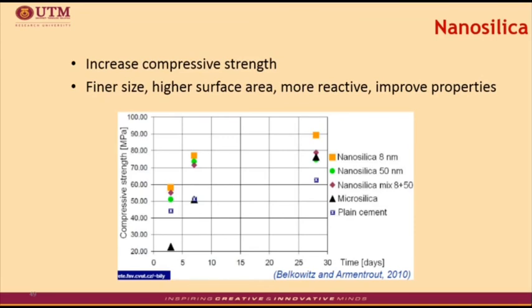This figure shows the results of compressive strength of a concrete tested at various sizes of silica from micro size to nano size, including conventional concrete. Based on the plots, it can be seen that the finer the size of the silica added to the concrete, the better the compressive strength. This is possibly due to the high surface area that could cause the nanosilica particles to become more reactive and improve the properties of the concrete.